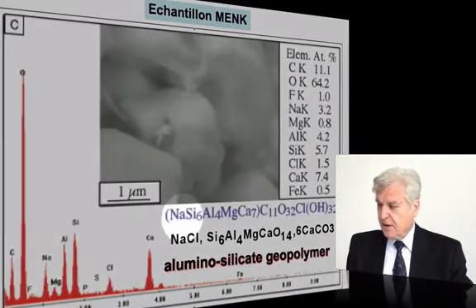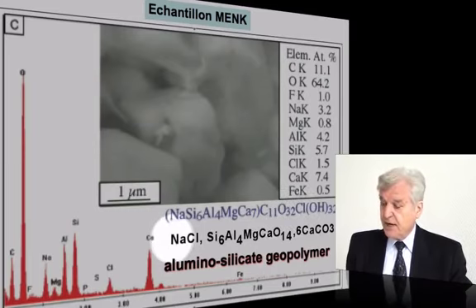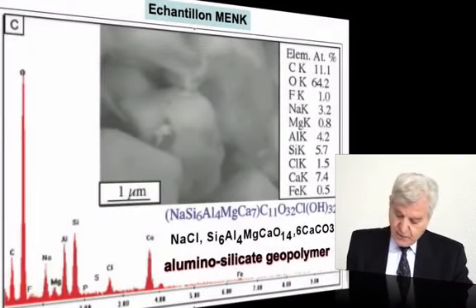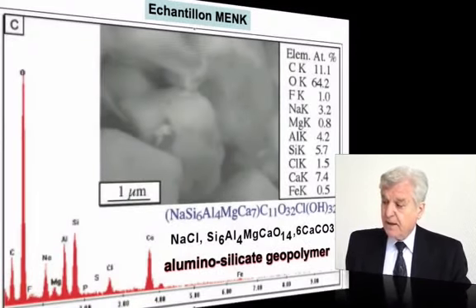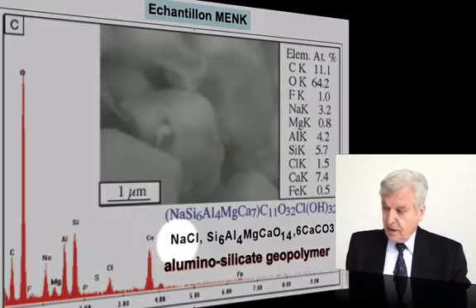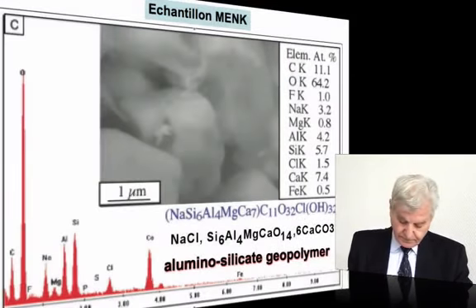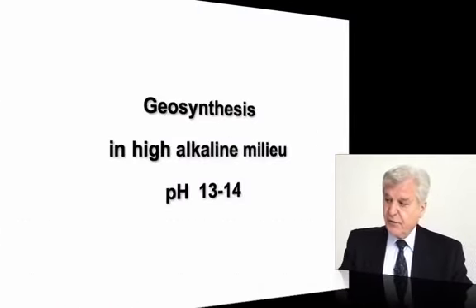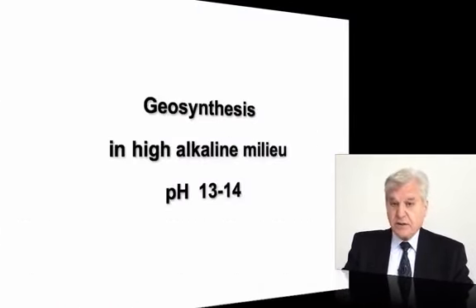As you see, it is a mix of sodium, silicon, aluminum, magnesium, calcium, carbonate, and chloride that represent NaCl, Si6Al4MgCaO14, 6 calcium carbonate. It is an aluminosilicate of geopolymer that has also sodium chloride and calcite in it. The authors confirmed that the matrix was the result of geosynthesis in high alkaline milieu, pH 13 to 14.